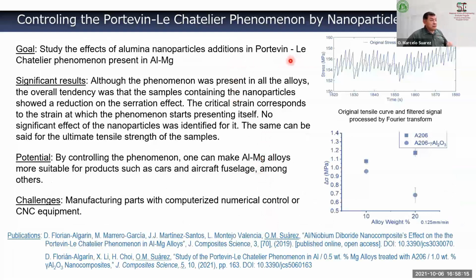With the same idea, I was reading at some point something about the Portevin-Le Chatelier phenomenon. If you don't know what that is, that's sort of an instability when you're pulling an aluminum magnesium alloy, where you end up having a serrated curve in the tensile versus strain curve. And that's a result of a plastic hardening, and then that's followed by a relaxation caused by the precipitation of these magnesium nanoprecipitates. So that if you're fabricating some piece made of aluminum magnesium alloys, you may end up having problems with that fabrication.